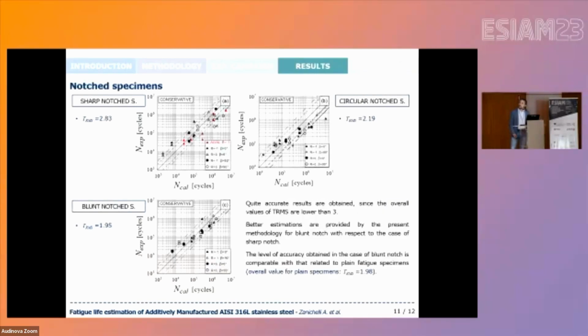And here you can see the same results for the notched specimens. In particular, also in this case, quite accurate results are obtained since almost all the results fall within scatter band 3. And this holds true irrespective of the loading configurations. So it can be highlighted that a TRMS value approximately equal to 2 has been obtained for both blunt and circular notched fatigue tests, whereas in the case of sharp notch, a quite higher value has been obtained.